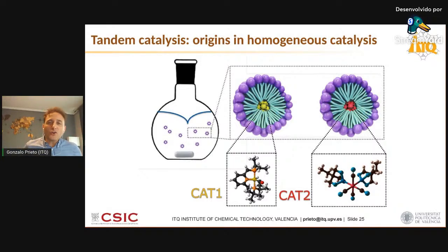This concept of tandem catalysis originates in the field of homogeneous catalysis back in the 80s. Researchers were combining different molecular catalysts, organometallic catalysts, in one single pot to steer two sequential and mechanistically decoupled reactions in one pot, as I said. And shortly after, researchers in general realized that a certain degree of compartmentalization of each of these two catalysts, so that the direct interactions and contacts between the two, which typically brings undesired and deactivating phenomena such as ligand exchange or agglomeration, even neutralization in some cases, if we are dealing with basic and acid catalysts and so on, it was beneficial.